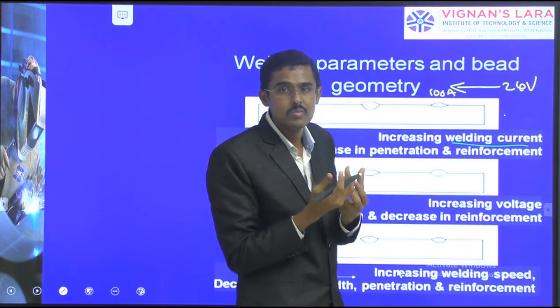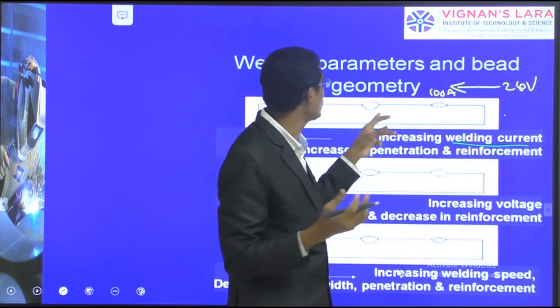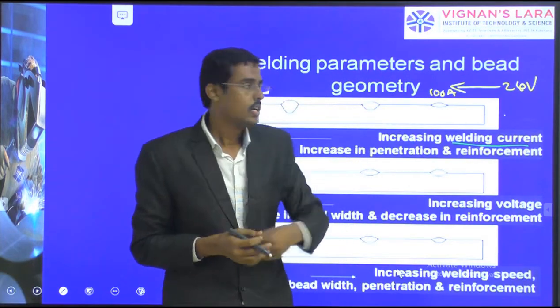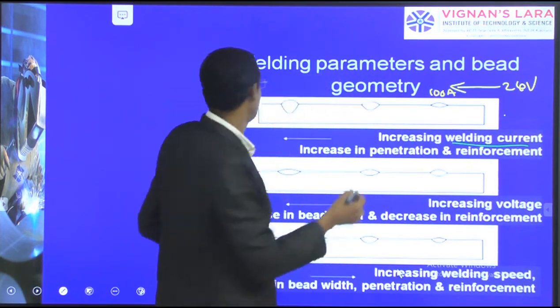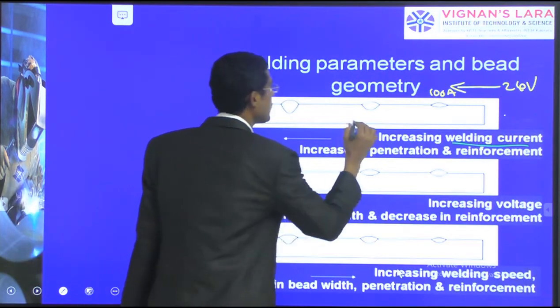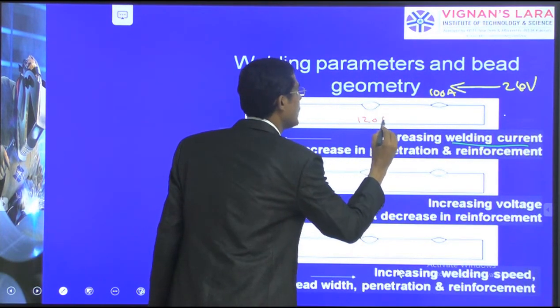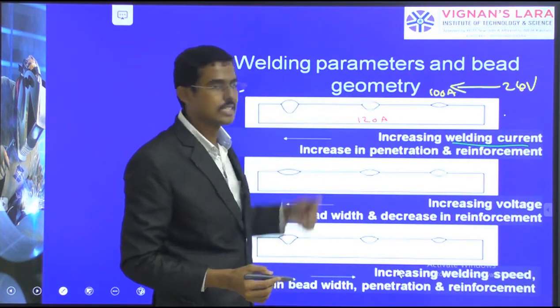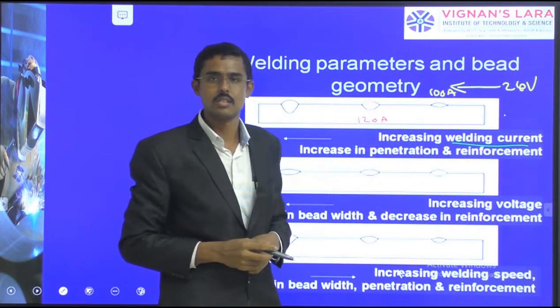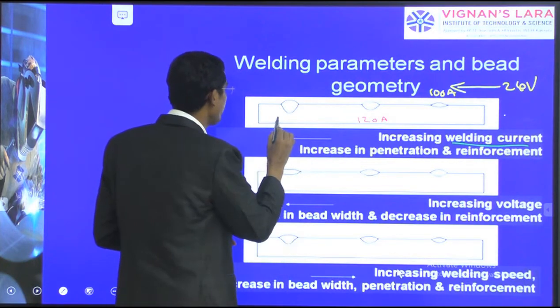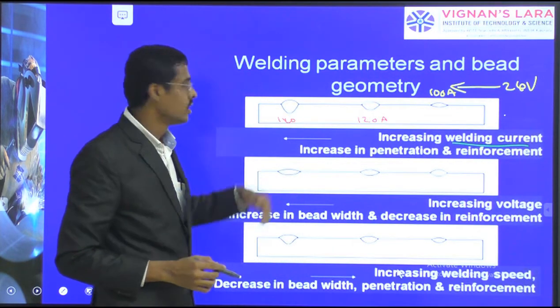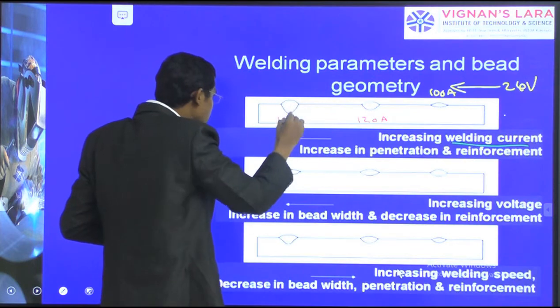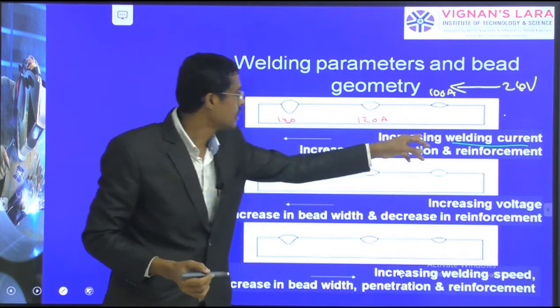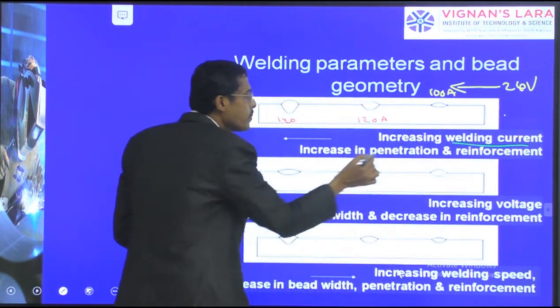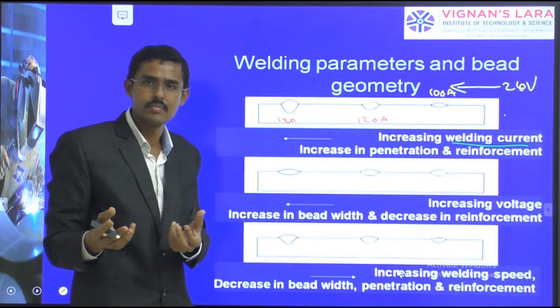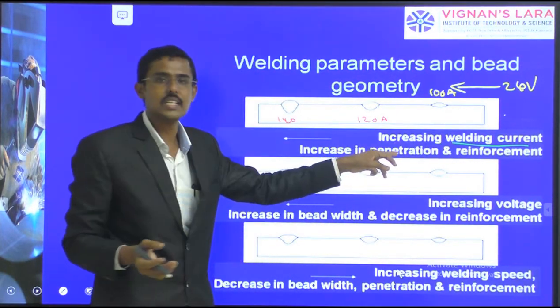It is low, but the required level is 120 amps. When the current is increased to 120 amps, what happens? The penetration increases. You see, from here to here, the penetration increases. Now, 120 to 140 I am increasing. Again, the depth of penetration increases. Increasing the weld current increases the penetration.